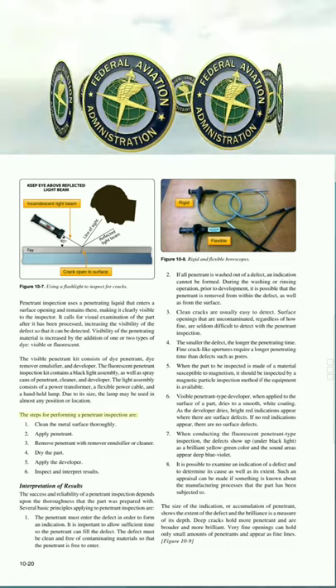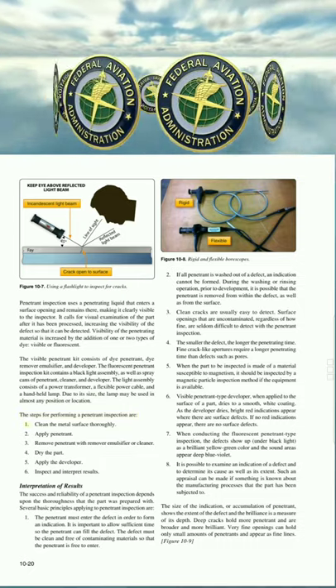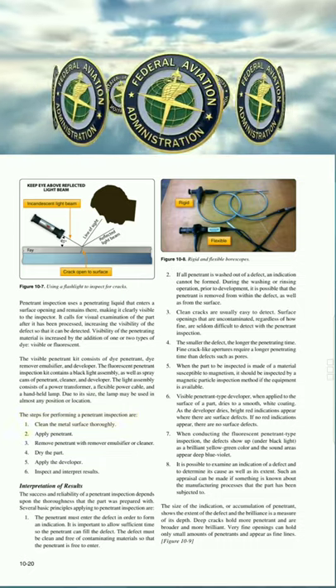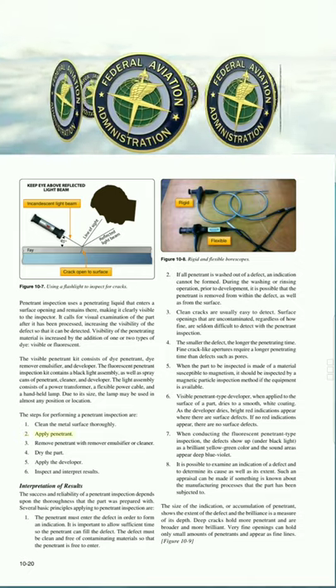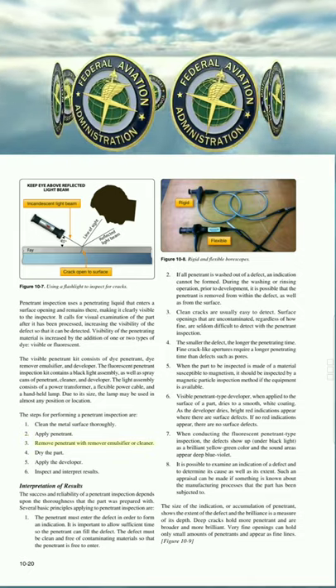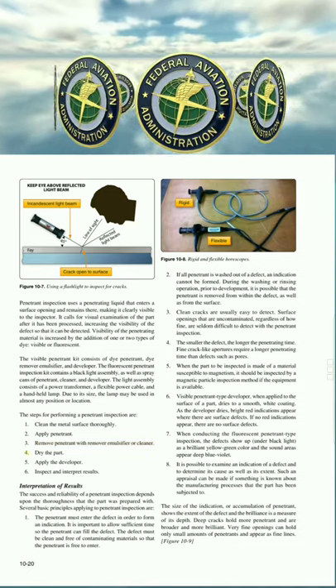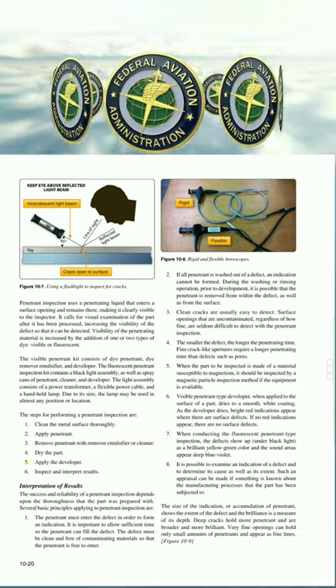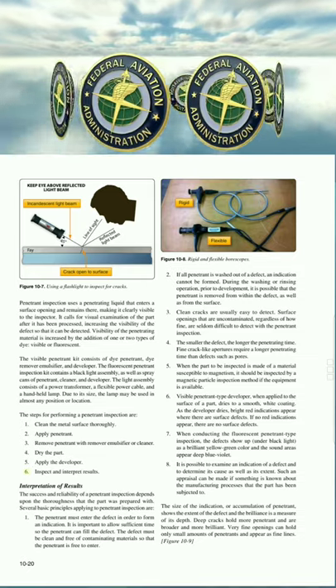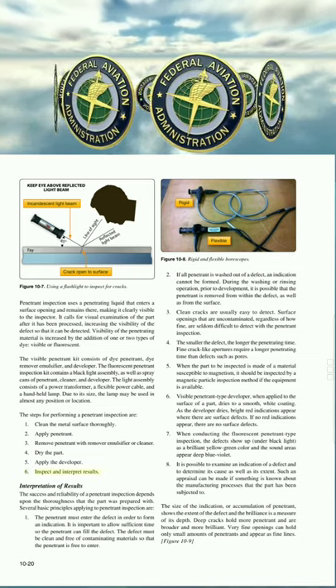The steps for performing a penetrant inspection are: 1. Clean the metal surface thoroughly. 2. Apply penetrant. 3. Remove penetrant with remover emulsifier or cleaner. 4. Dry the part. 5. Apply the developer. 6. Inspect and interpret results.